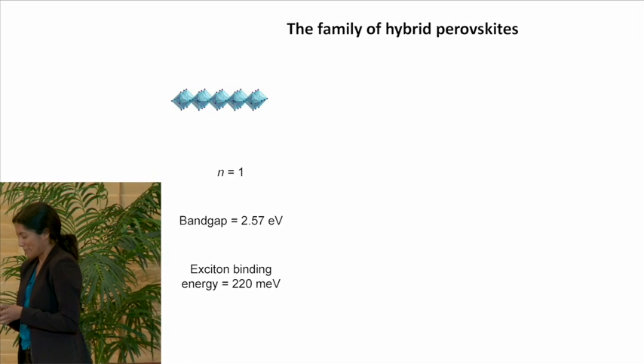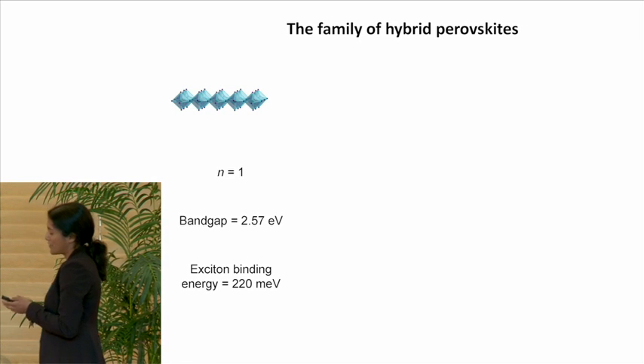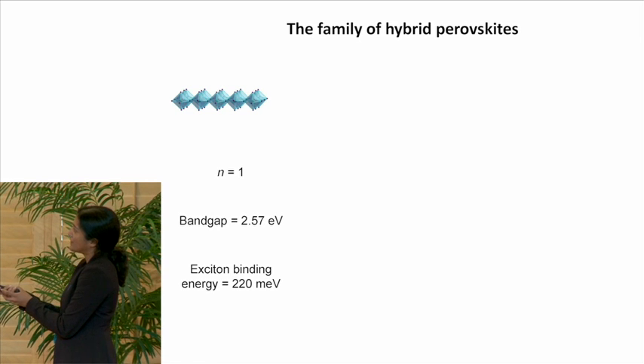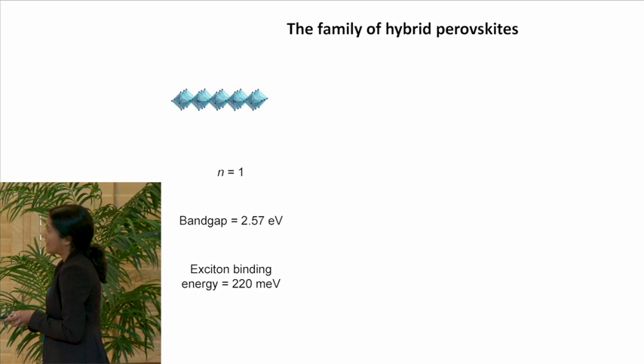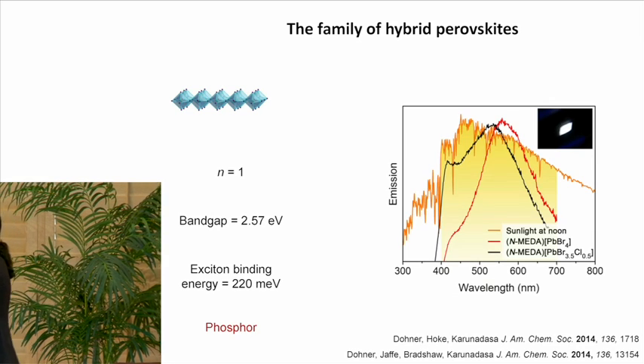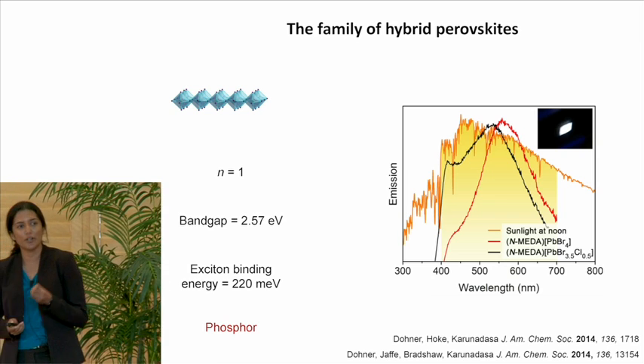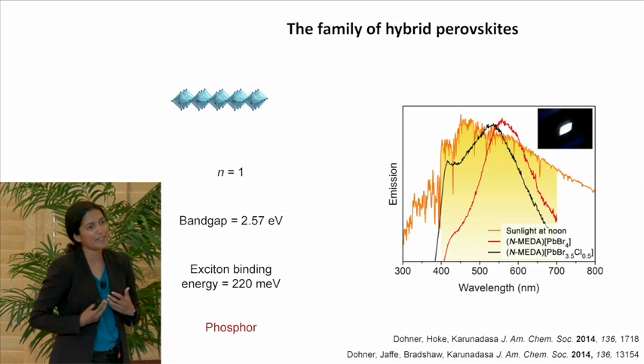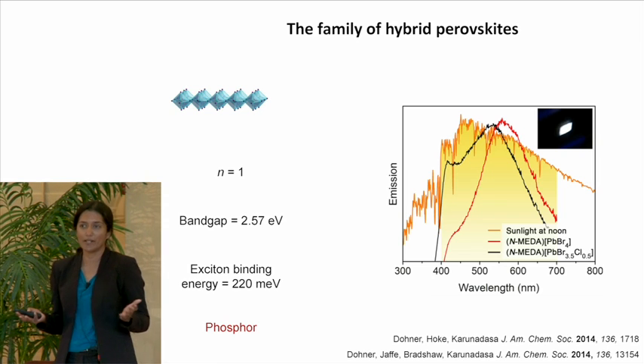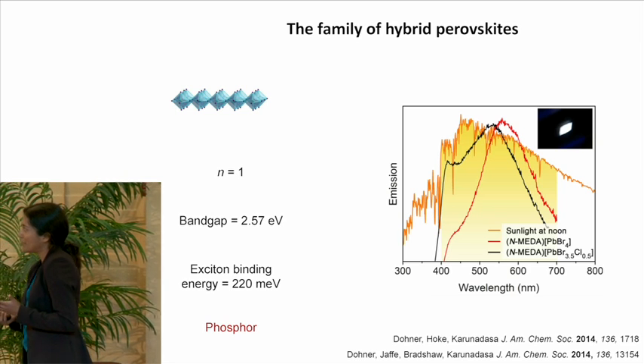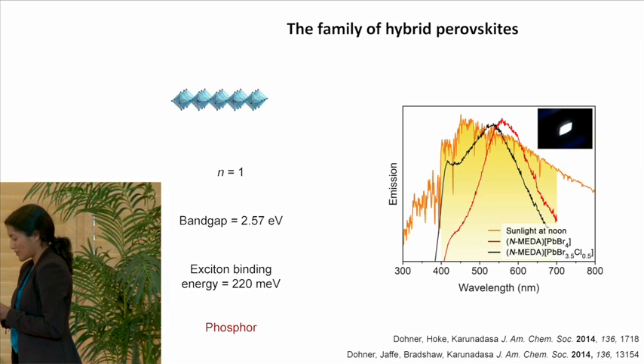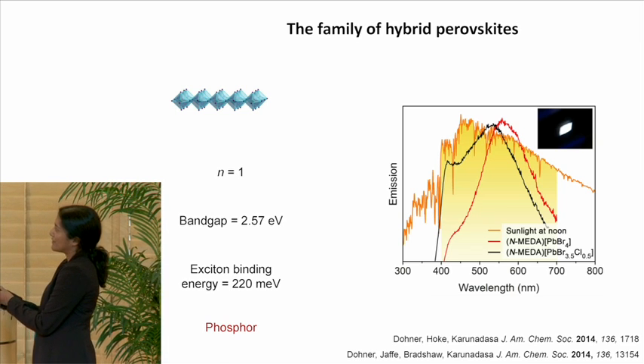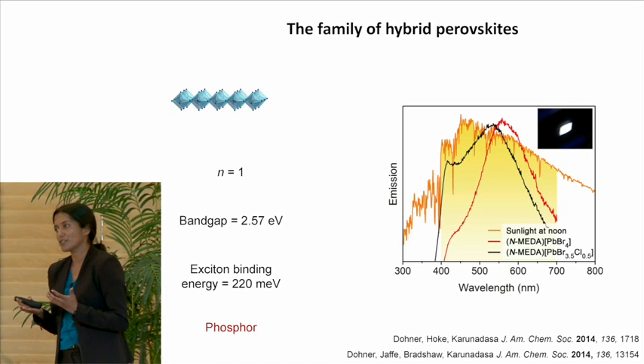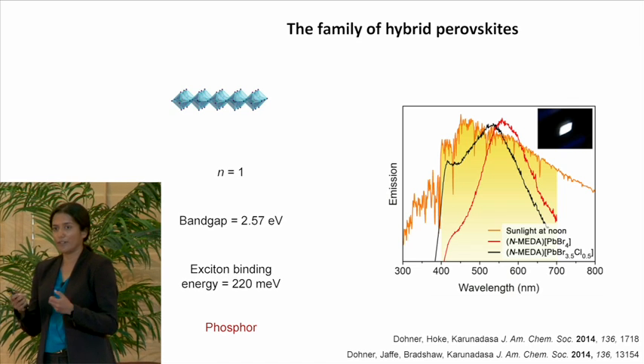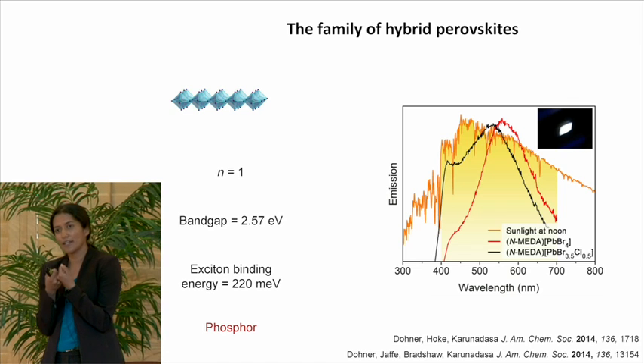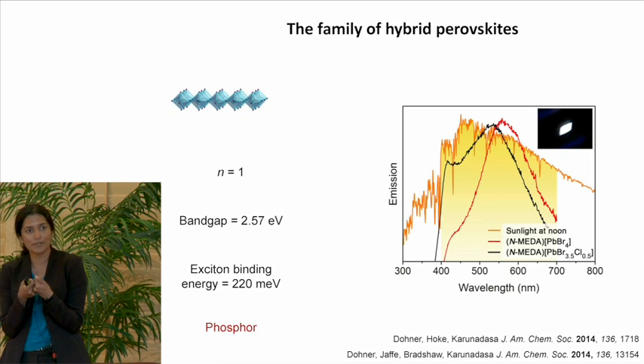And we know that these materials have other advantages. We've found that some materials which have these n=1 sheets are actually very nice phosphors. So when we hit this material with blue light or with UV light, the material emits white light, broadband white light, which looks like sunlight. And we know that the reason you get this emission is because this layered material gives rise to electronic structures which induce very strong exciton binding energies, as well as very localized charge carriers.